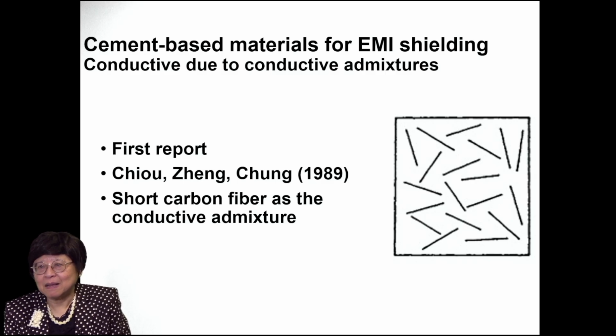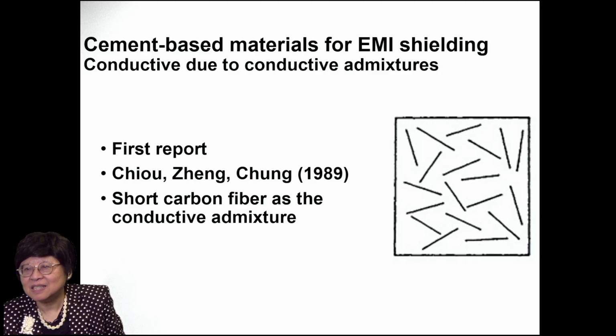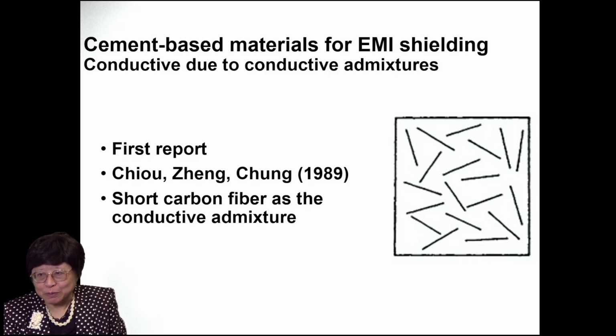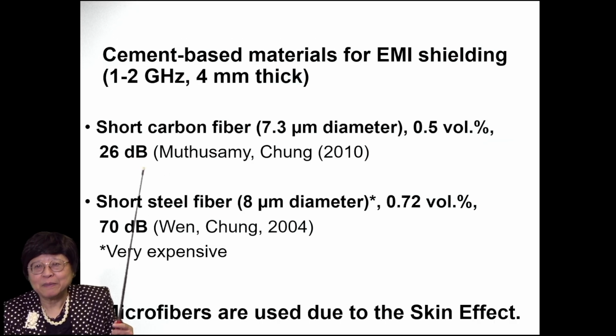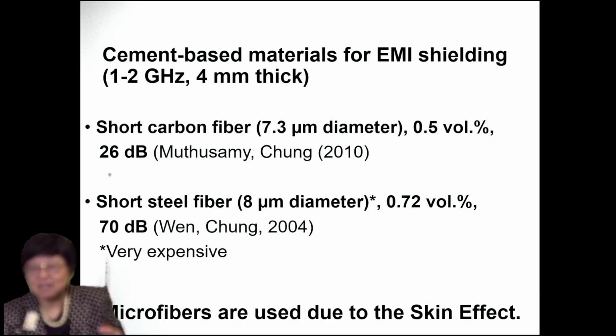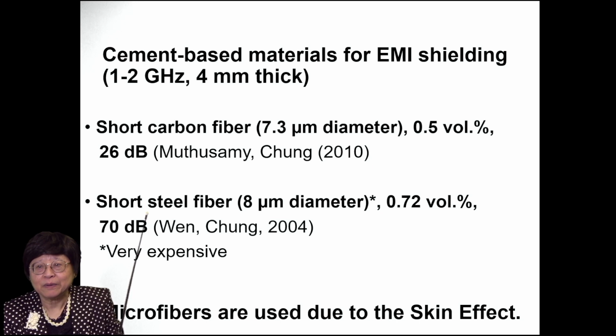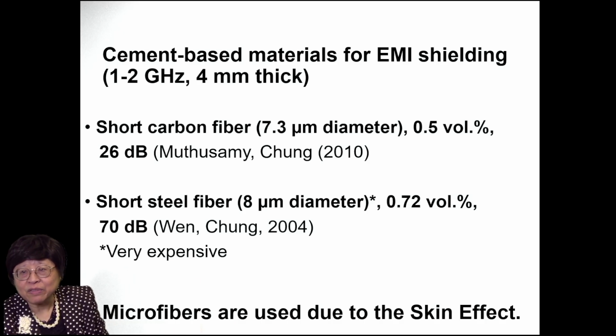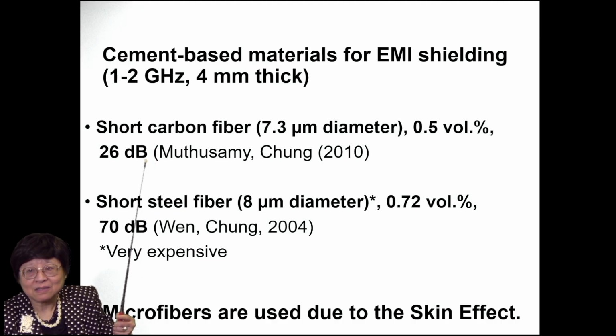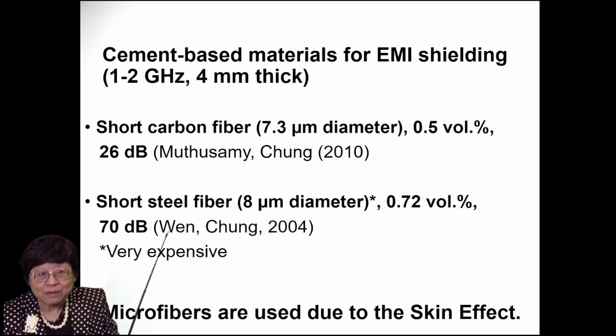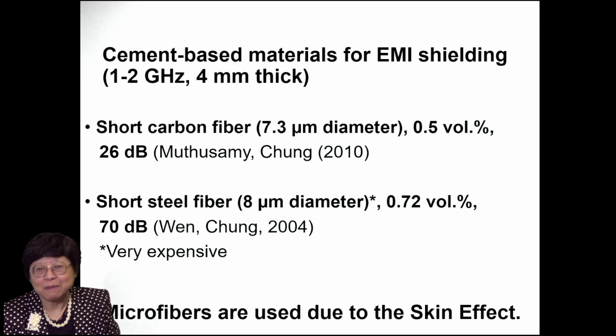I was the first that reported about cement-based materials being able to provide EMI shielding back in 1989. And since then, I've improved. Short carbon fiber inside the cement-based material, 26 dB. But if one goes with short steel fiber, it's a lot better, 70 dB, because the steel is a metal, it's very much conductive, and also it has some magnetic character. But note that both are microfibers. That's important. If it's nano, it's even better. But these are micros. And if one uses the macro fibers, it would not be effective. And microfibers are used because of the skin effect.